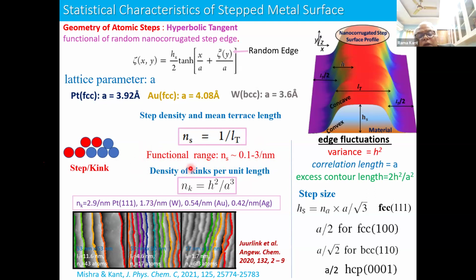And we obtained a formula which did not exist earlier, like even the density of kinks per unit length, which is the fluctuation at the edge, the mean square fluctuation. This is h squared, a is my lattice parameter, and this and the lattice parameter give me the kinks per unit length. And this we obtained by fitting our theory for work function to the data which is available for step density dependent work function for various metals. And from fitting our data, we could figure out NK through our equations, which is not available in literature.